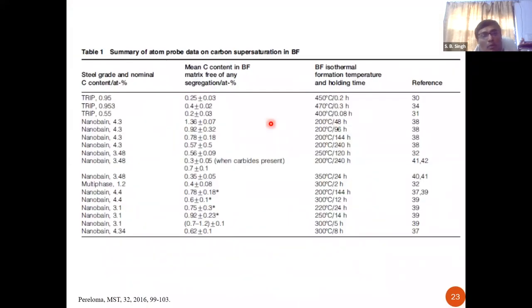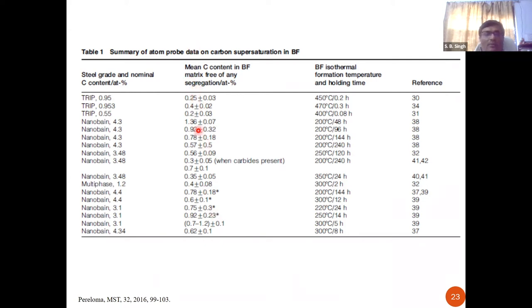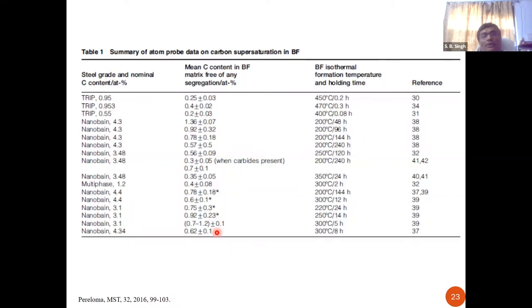In more recent years, there are a lot of data indicating that the carbon content of bainitic ferrite, away from segregation locations, is much higher than usually believed. There is a small temperature dependence in the sense that at lower temperatures, the carbon content of bainitic ferrite is higher. It does not easily relieve its excess carbon even after long tempering treatment, suggesting it continues to hold this excess carbon.